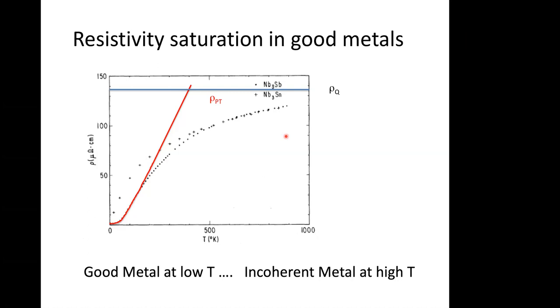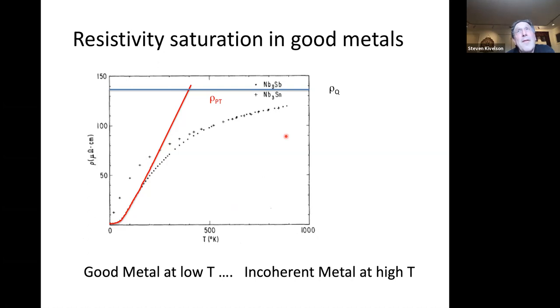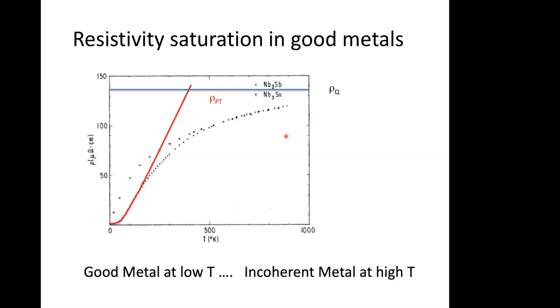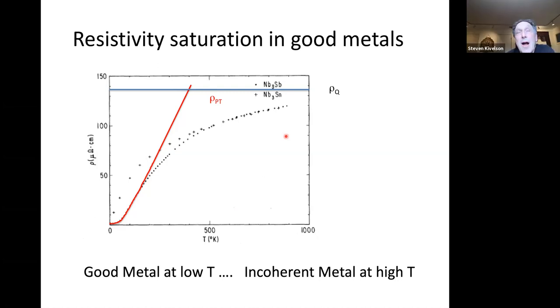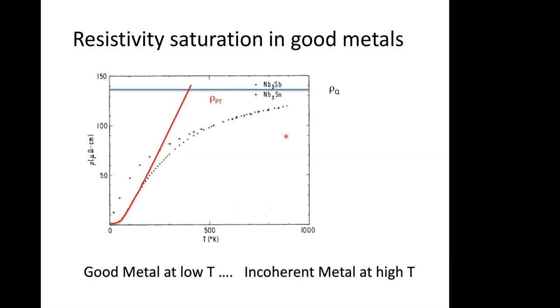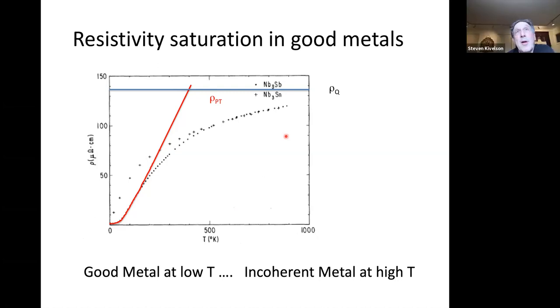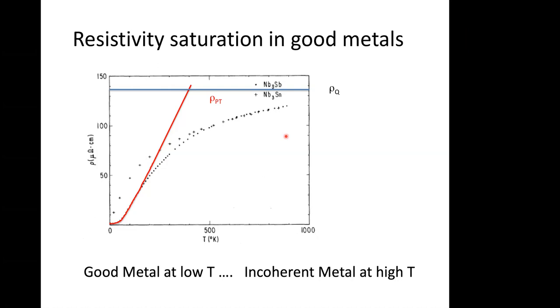Is that true? If it's all momentum scattering, I go to the exact eigenstate representation and there is no lifetime at all. It's just that I do not know how to do the calculations. Well, but I don't have a coherently propagating quasi-particle then. K is not a good quantum number. I completely agree. But I still have quasi-particles. They just cannot be described by K. Right. Probably in the liquid metals that I've looked at, the energy scattering rate is much, much slower. That's right, mostly elastic scattering.